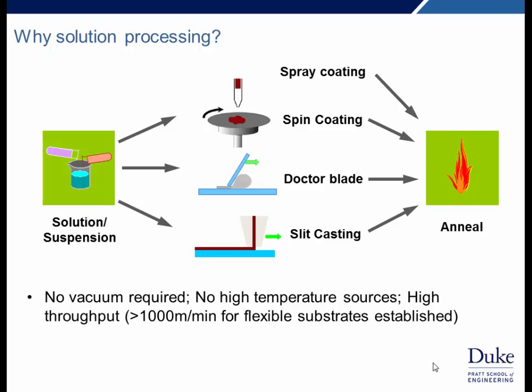In addition, solution-based deposition is very simple. We just take the relevant materials, dissolve them in an appropriate solvent, and then deposit these onto a substrate using well-known techniques: doctor-blading, slit casting, spin coating, and ultimately heat treat it. The heat treatment is to evaporate the solvent, perhaps to decompose a precursor, as well as to induce grain growth.